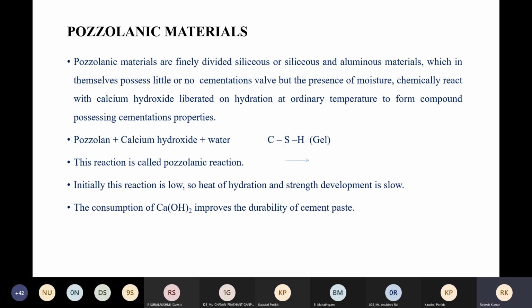So initially this reaction is low, so heat of hydration and strength development are also slow. The reason is, suppose you take the pozzolanic material fly ash, initially for 6 or 7 days it is in the dormant position, but when calcium hydroxide is liberated due to the remaining OPC cement, that reacts with the pozzolanic material, and in the presence of water it forms the calcium silicate hydrate. So this reaction is slow. Due to that, heat of hydration is low and strength gain is also slow. So the consumption of Ca(OH)2 improves the durability of cement paste.